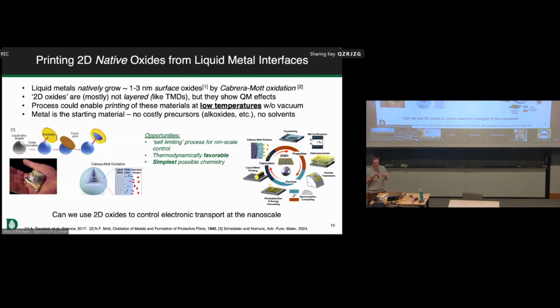But in doing so, that liquid metal, it's compliant, it's low viscosity, and it essentially preserves the structure of that thin film without destroying the surface oxide. Now, this is surprising for a few reasons. One, that surface oxide grows just a few nanometers thick. So this is a corrosion process that happens just like you would imagine another metal oxidizing, but depending on the metal you use, the kinetics of that process change significantly. So this group, they showed that you could do this on a small scale. We've been working on demonstrating the same method on a much larger scale, at a wafer scale or panel scale for thin film flexible electronics, and applying it to a number of different devices as well.